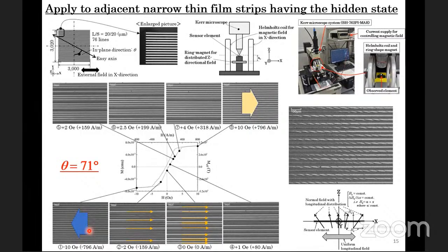The element switched the direction of dipole as the external field changed. The magnetic mutual interaction between elements makes the direction transition gradual, as if they were affected by the demagnetizing force. When the distributed normal field was applied, the transition towards the multi-domain state was observed, as shown in the right figure.